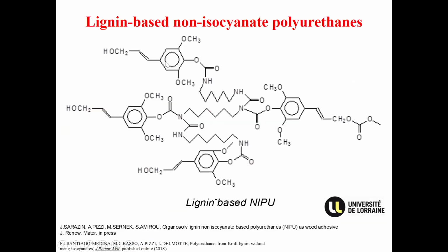Same with lignin. Those species we isolated. We had lignin. The carbonate reacted with the OH of some unit of lignin, and the diamine, and the carbonate reacted with different parts of the lignin or different OHs of the lignin. Even with the aliphatic OHs, it reacts. But these species that you see there have actually been isolated and identified.